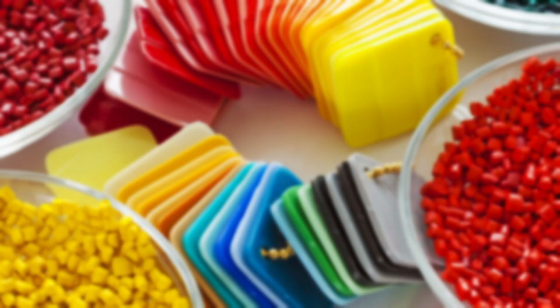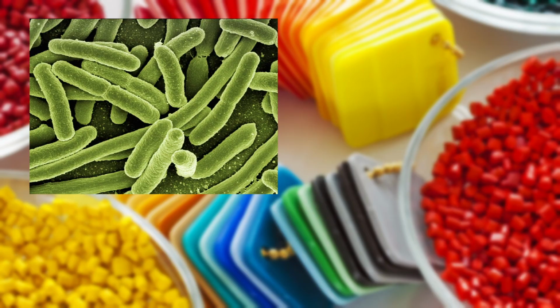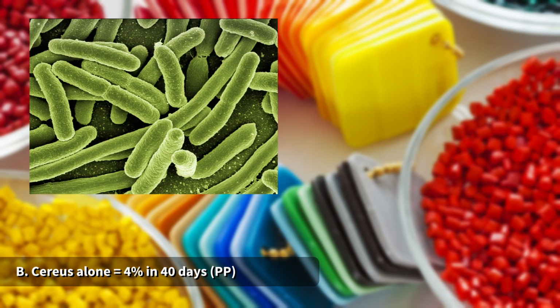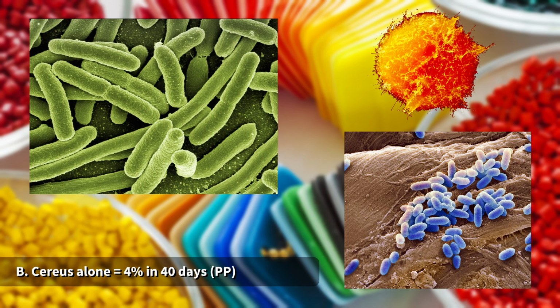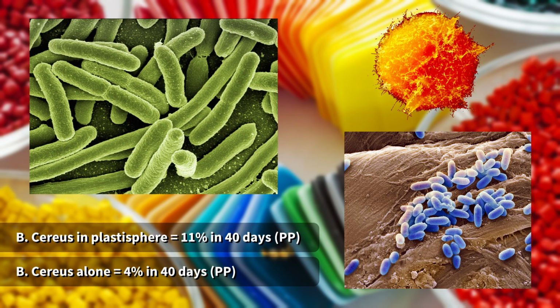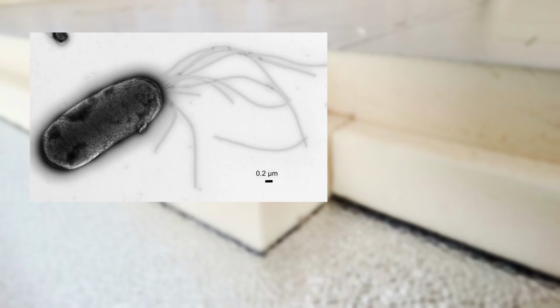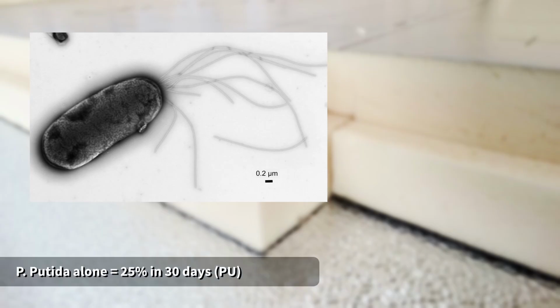Let's talk numbers. Bacillus cereus alone can degrade polypropylene microplastics by about 4% in 40 days. But when polypropylene is colonized by marine plastisphere communities, that number jumps to 11% in the same time frame, nearly 3 times more. Pseudomonas putida degrades polyurethane foam by 25% in 30 days.